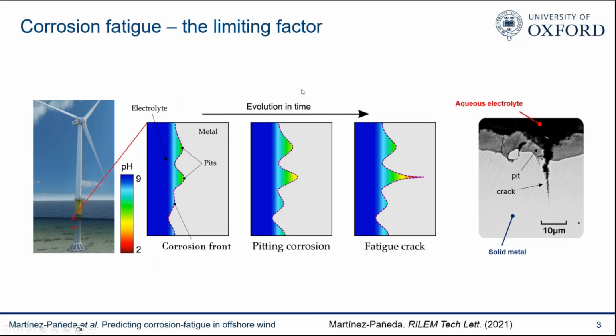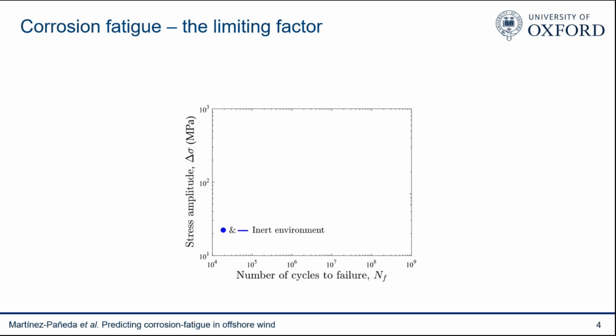So how do we incorporate this complex phenomenon into current offshore design? Well, we do that using something known as S-N curves, which I can explain in a minute for those of you not working in this field. You basically go to your lab, you test a simple cylindrical bar under cyclic loading, and record the number of load cycles at which failure occurred.